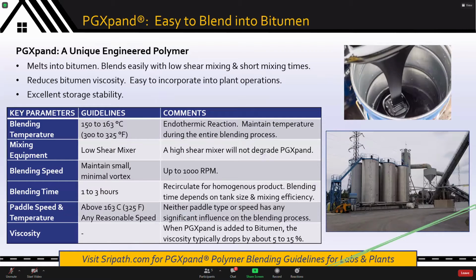So how do you use this in a lab or in a plant environment? Very easy to mix in. Temperature ranges typically of about 150 to about 163 degrees C. Low shear mixing, paddle wheel mixing is more than enough. You do not need high shear mixers. However, use of high shear mills does not degrade the PGXpand or the bitumen.